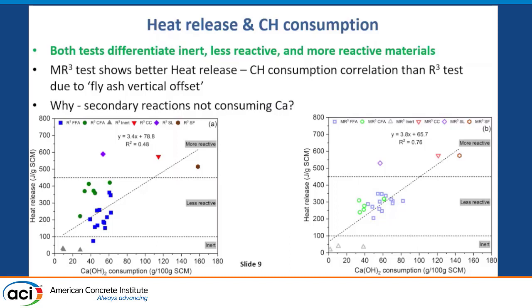If you want to use these in specifications, what values do you use? Personally, I like 100 joules per gram — you can go a little bit higher or lower, it doesn't matter all that much. We really haven't seen anything reactive below 100 J/g, whether you run an R3, a modified R3, or a variant. There might be some caution needed depending on kinetics, but for the most part, 100 is a nice differentiator between reactive and unreactive materials.